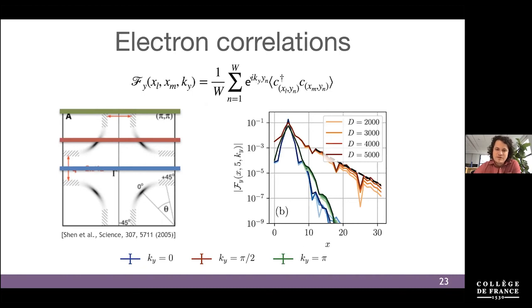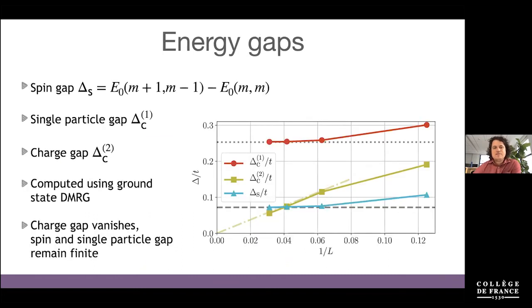And what I'm showing you here is a result of this quantity here. And this is only shown at 0 temperature. What I'm showing you is this correlator as a function of the distance between the 2 different sides. And what is shown here is that at ky equals 0 and ky equals pi, this electron correlation is decaying very quickly, exponentially. Whereas at ky equals pi over 2, this is decaying rather slowly. This indicates a smaller gap. So we can now actually estimate those energy gaps precisely.